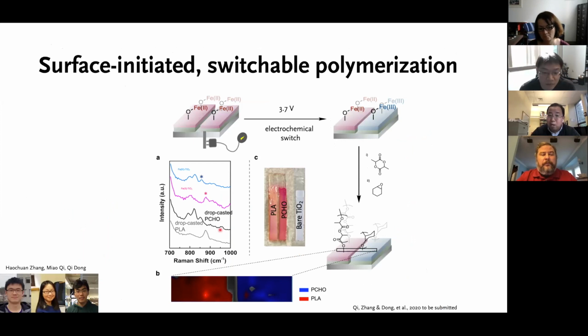We can characterize it by a number of methods. IR showed us that we indeed have polylactide here, and also polyepoxide on the other side. But we used a tool that can give us spatial information, a scanning Raman spectrometer, and then we can use characteristic peaks of these two different chemicals. We can map out how the distribution is. And if you don't believe me, you can also look at the dyed surface, PLA, PCHO, they dye differently. The dye here we use is rhodamine 6G. And then it clearly shows that by a single step, a mixture of precursor polymerization, we get the different chemicals on the surface. It's a very small step forward.